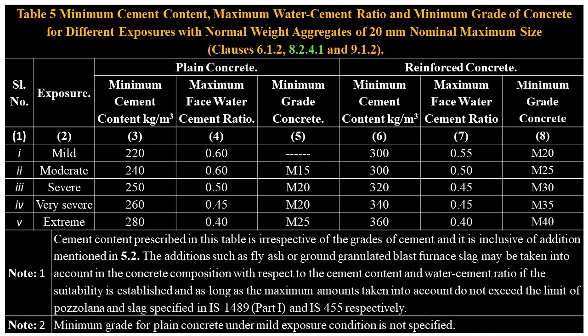Plain concrete, minimum cement content 280 kilograms per cubic meter. Maximum free water to cement ratio, 0.4, grade of concrete, M25. And for reinforced concrete, minimum cement content 360 kilograms per cubic meter. Maximum free water to cement ratio, 0.4, grade of concrete, M40. Below Table 5, there are 2 important notes to consider.